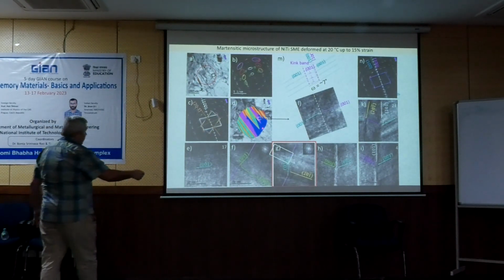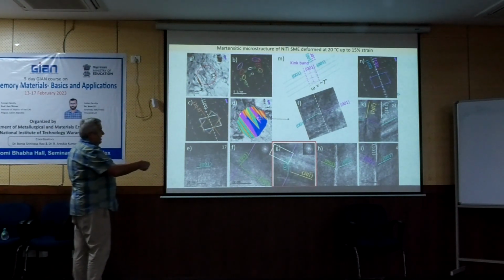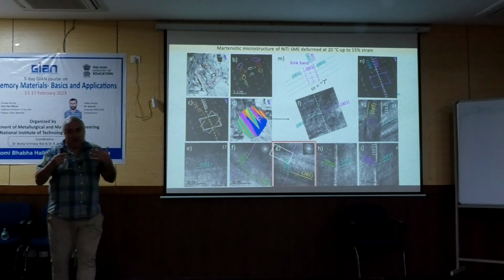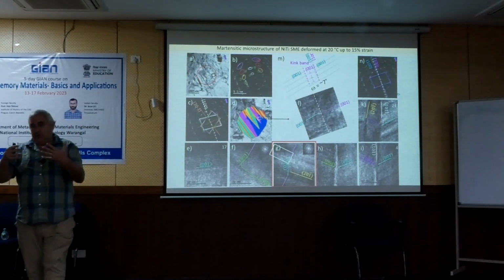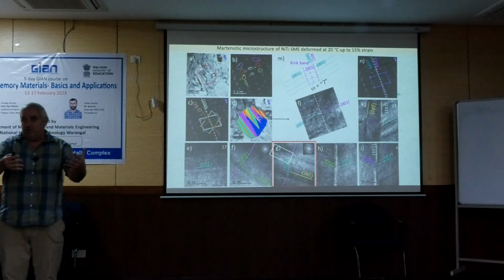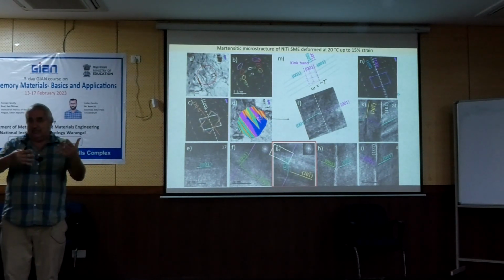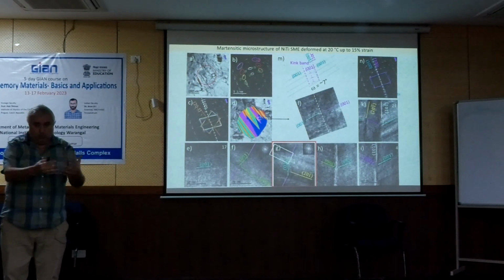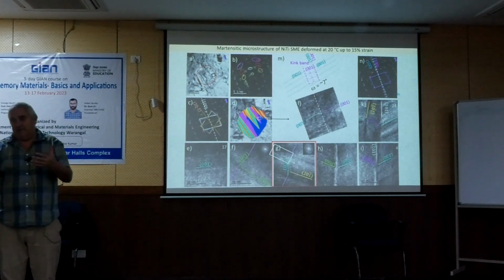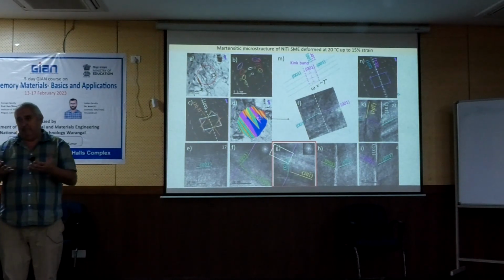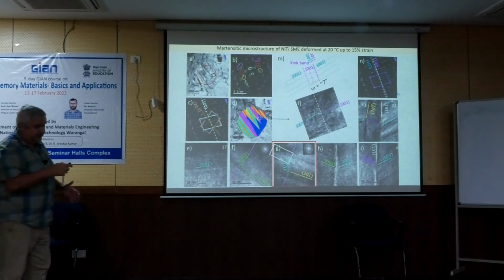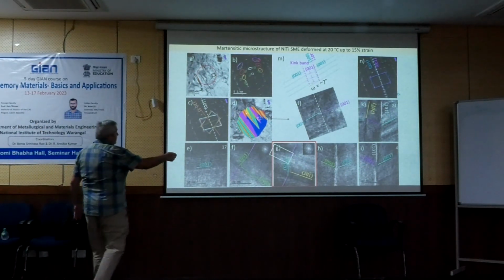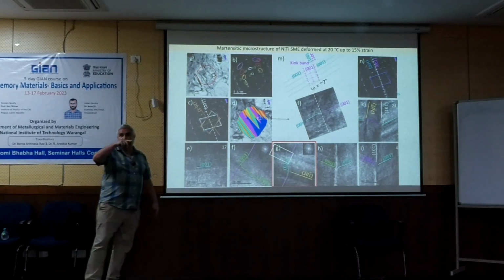There is only a limited set of deformation gradients, but they are not only those known in the literature, which can be calculated using the Bhattacharya approach from the lattice parameters, but those plus some others created by slip. And they have to fulfill the same condition, this incompatibility, this m times b.